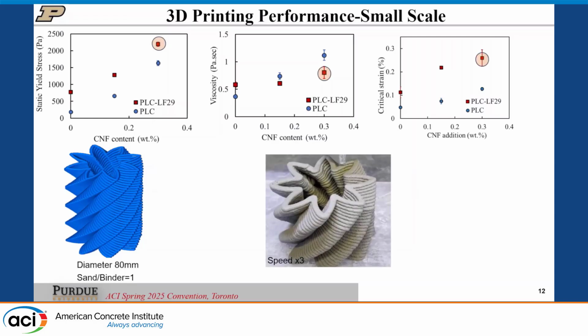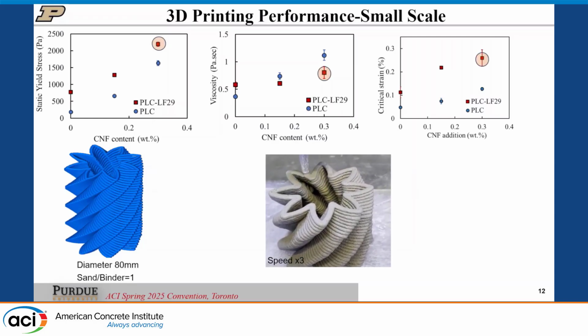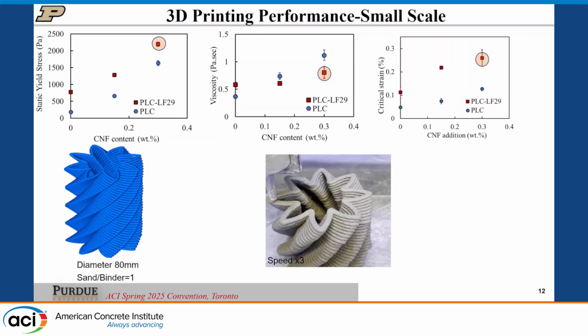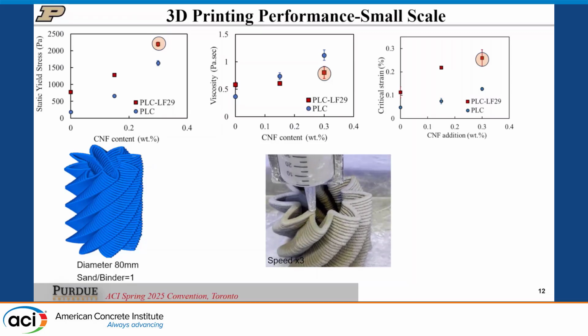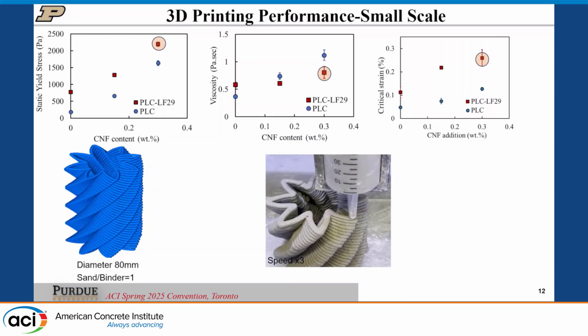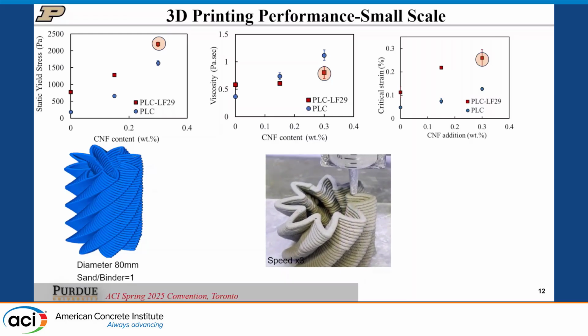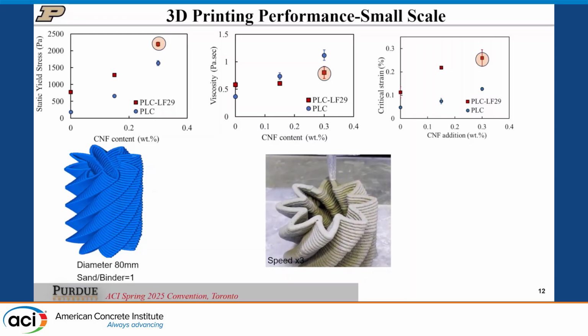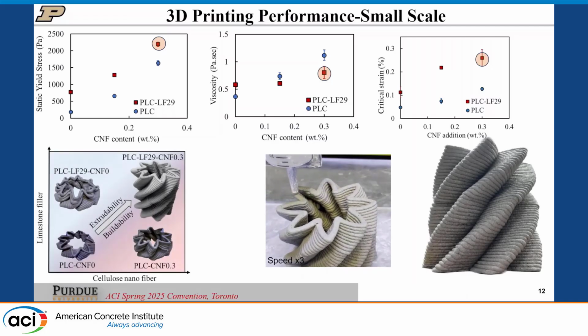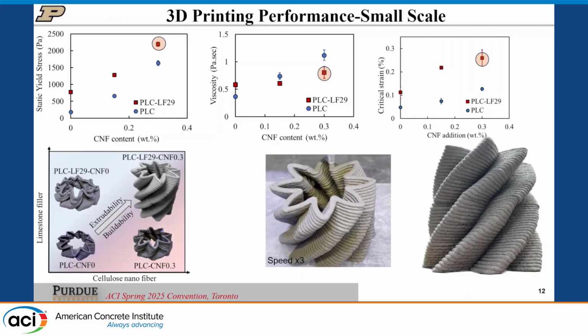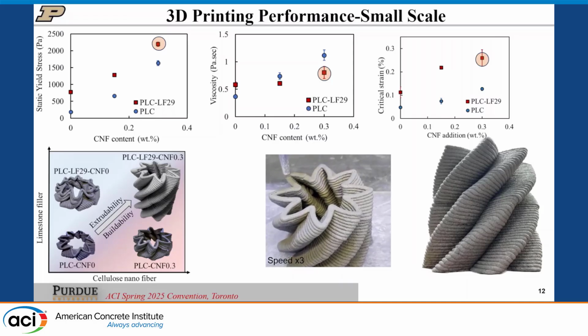Lastly, with the mixture having high static yield stress - high limestone filler content with 0.3% CNF - this is where we obtained really good printing performance, which meant we needed both parts of the system to achieve this good printing performance.